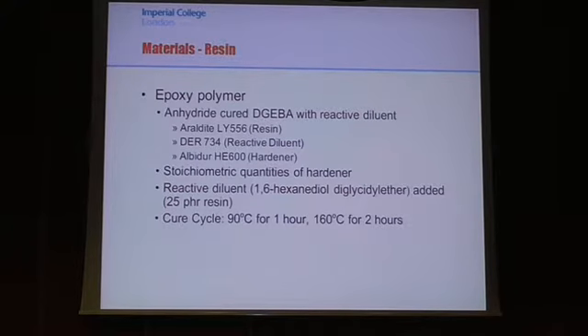So, I used an epoxy polymer, which was an anhydride cured DGEBA. I mixed this with a reactive diluent, which lowers the viscosity of the epoxy, which allows it to be used much easier for processing in terms of carbon fibre infusion technologies.